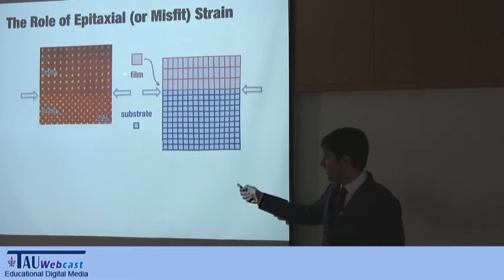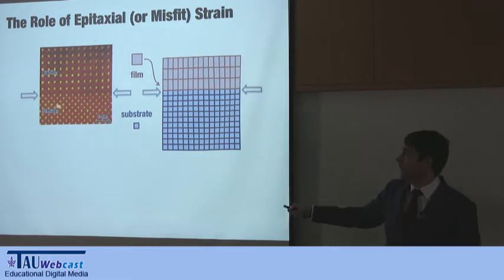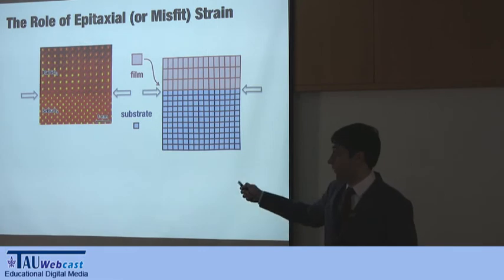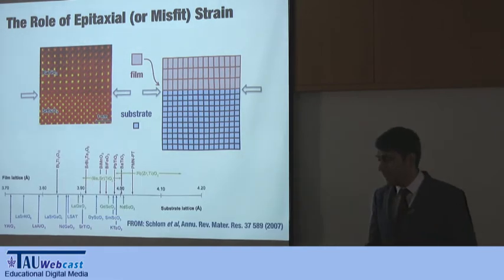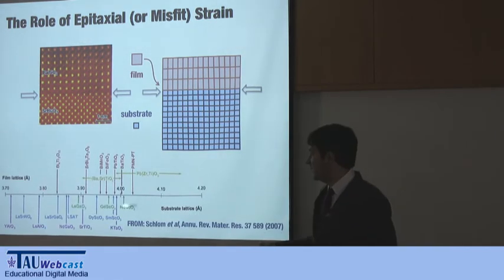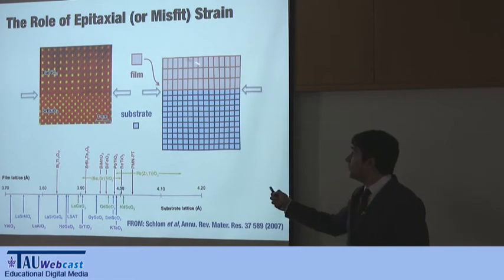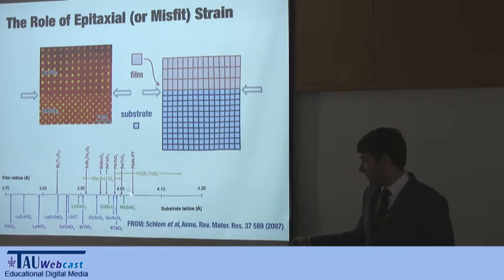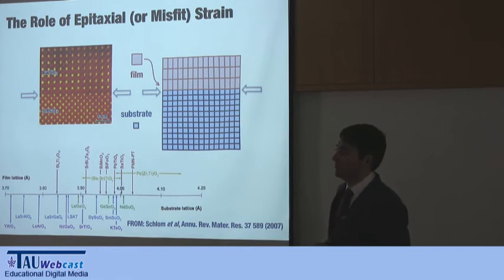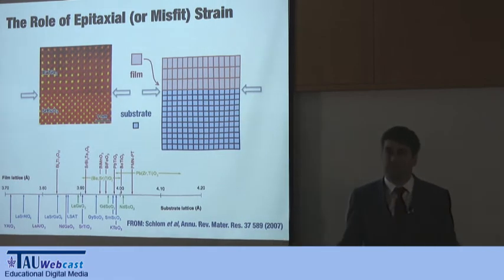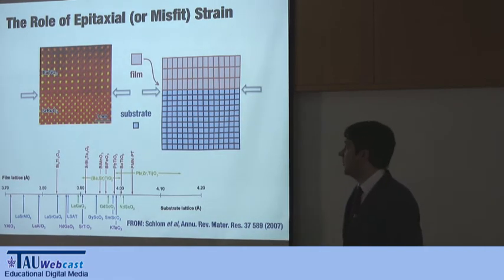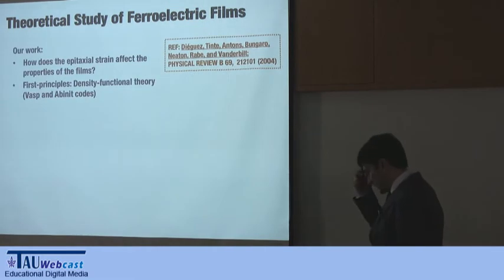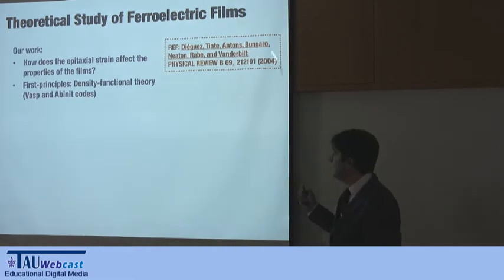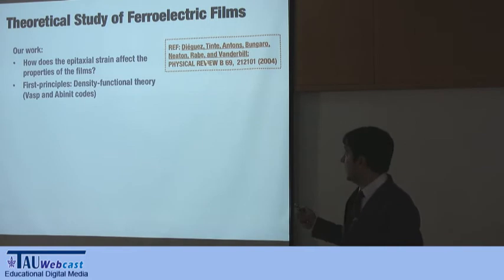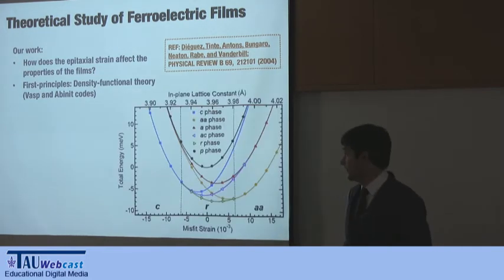And you can grow them in the lab for hundreds of nanometers, even coherently. So this, as I said, gives you a handle on what you want to do with your film. You just pick the substrate you want, and then your film will be more or less compressed. Let's see what happens when they are more or less compressed. And this is a work that I did in the group of David Vanderbilt and Karin Rabe, and we used density functional theory to do this.